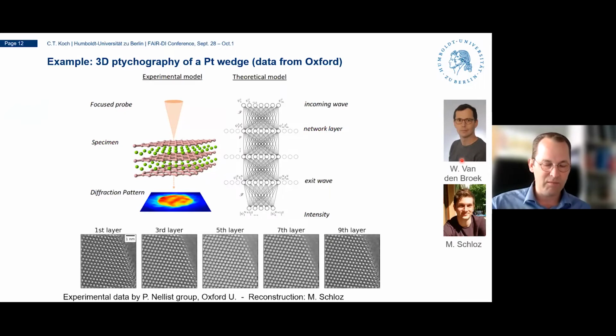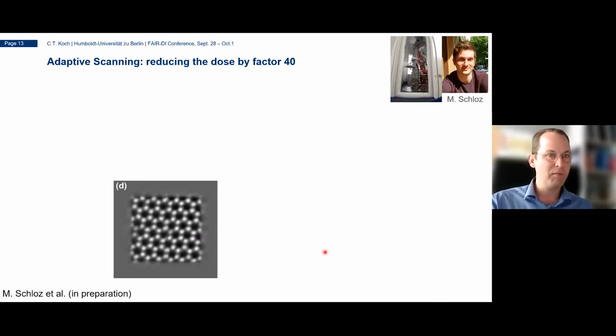Here, one last example I wanted to give is ptychography. It's a compute-intensive technique where you have your sample and you position your beam at different positions across your sample, and you collect diffraction patterns at each beam position. Then you can reconstruct using a layered structure that's like an artificial neural network that at the bottom produces your experimental data, but within the structure, you have the three-dimensional potential that scatters your electrons. So there's a very nice physical representation of this actually. And then you can reconstruct the layers of your material that have scattered your electrons. And once you implemented that, you can even train the computer to control your microscope, to position the beam to where you would most efficiently expect more data to build the structure.